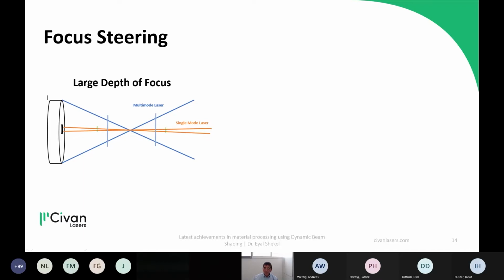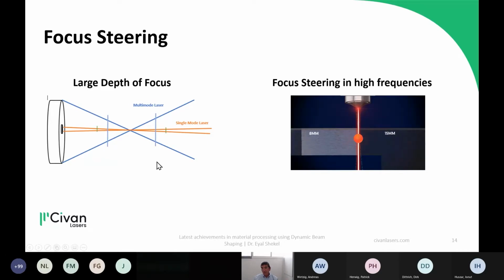Another important property of our laser is the fact that it's single mode, which means that the depth of focus is very large. So inherently, when you compare a multi-mode laser, in the blue you see, to a single mode laser, the depth of focus is already much higher with a single mode laser. But in addition to the inherent depth of focus, we can actually control the focal point to achieve even larger depth of focus. And this can be done, again, just like we can move the beam in the XY, we can also move it in the Z. And again, this can be done at 10 megahertz over a range of a few millimeters.